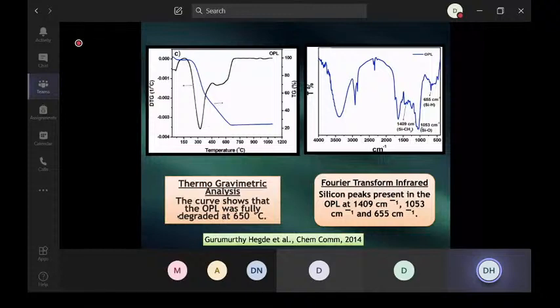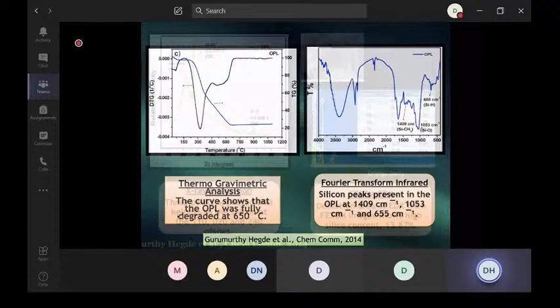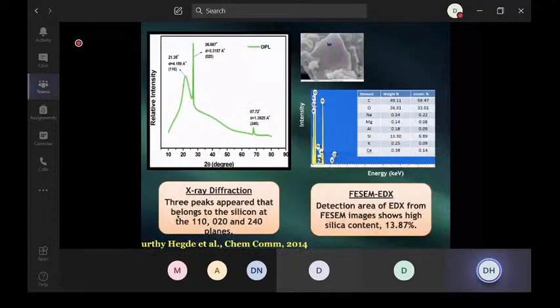If you want more details about it, you can go to our paper published in ChemComm in 2014 on this. Then we subjected the precursor to XRD, and you can again see the silicon peaks appear at 110, 020, 240. They belong to the silicon planes. Then again we subjected it to FESEM EDAX, and again we got the various percentages. You can see the silica percentage is 13% in this particular OPL. It's very high for any bio-waste material that I can list here. Silica content 13%. Why this 13% is important, you will come to know very soon.